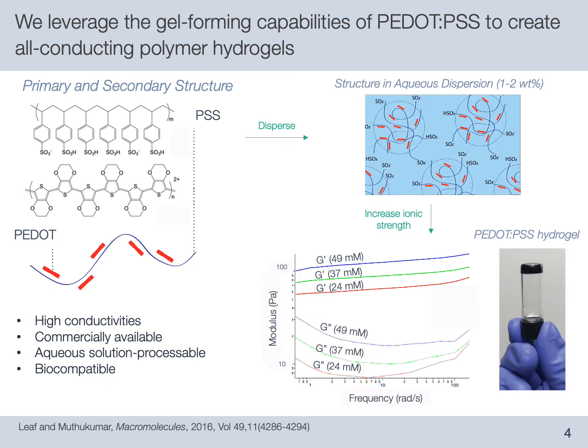When dispersed in water, PEDOT:PSS takes on a colloidal structure comprising dilute nanogel particles that electrostatically repel each other due to the negatively charged PSS groups. We found that increasing ionic strength could destabilize these colloids, resulting in a colloidal hydrogel where the storage modulus is directly proportional to ionic strength and where storage modulus exceeds loss modulus, indicating solid-like behavior.